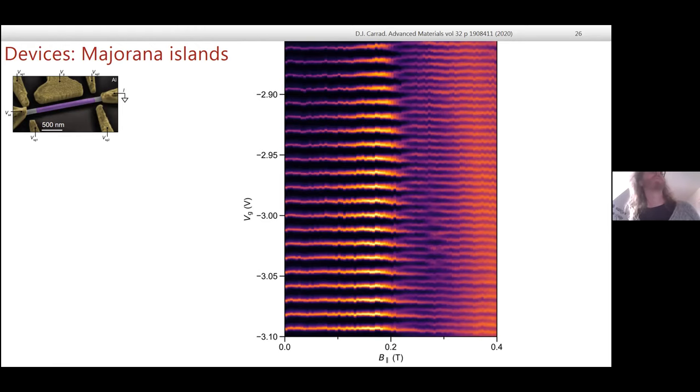And so these kinds of experiments have been done before, but what was strongly limiting in the past was that you could do an experiment like this and say, okay, maybe it's a certain kind of state, and then move to a different gate voltage configuration and change your device around a little bit and see different kinds of states. But perhaps you wouldn't be able to come back to your original gate configuration, because uncontrolled charge switching would completely change the picture and you wouldn't be able to recover your original state. This is probably due to etching causing damage or other kinds of things.